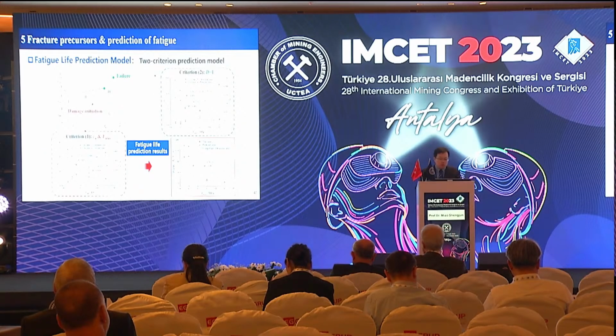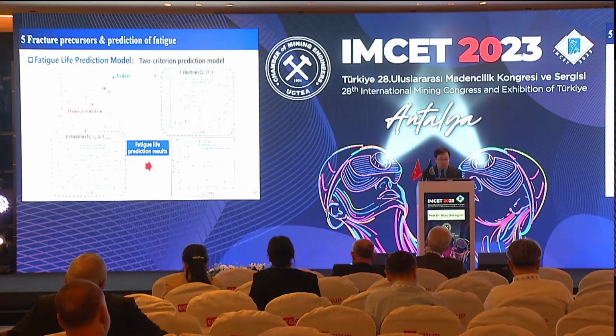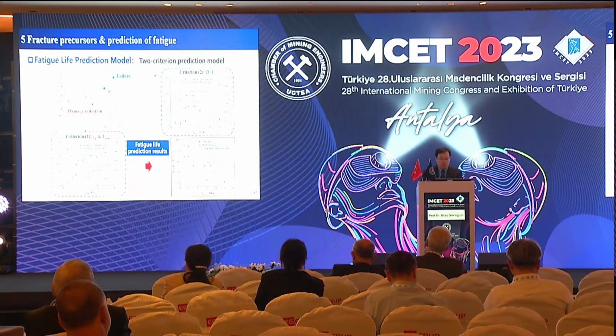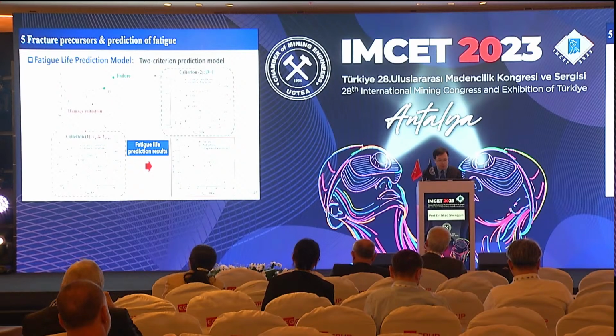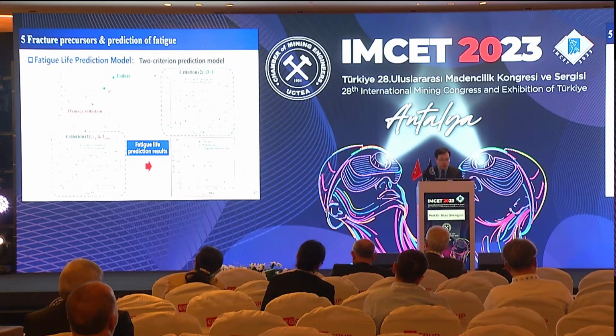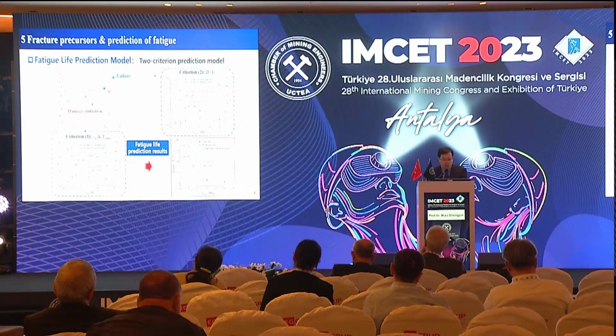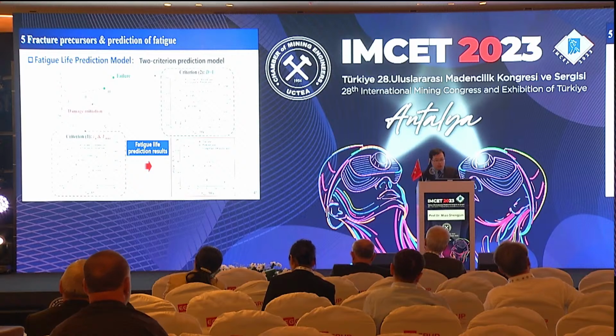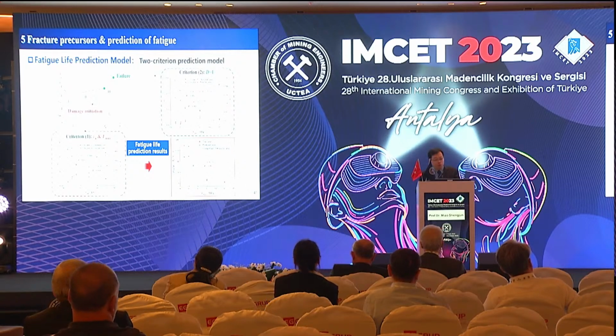Finally, we proposed two criteria to predict the fatigue life of the rock. The first criterion determines when rock enters the accelerated deformation stage based on the fatigue ultimate strain. The second criterion determines the duration of accelerated deformation based on the evolution of the damage variable. By combining these two criteria, we can obtain the complete fatigue deformation time of rock and predict its fatigue life.